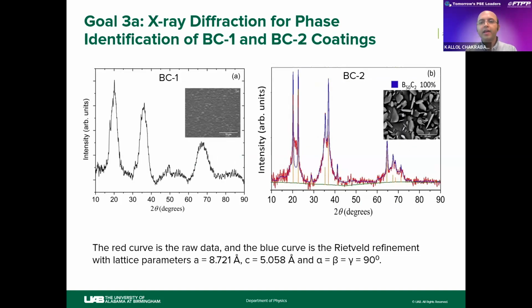Next, we did the X-ray diffraction of our two different coatings. As I mentioned before, our sample which was synthesized on the flat sample holder has amorphous nature, and according to the XRD as well, you can see a big hump in the XRD pattern.